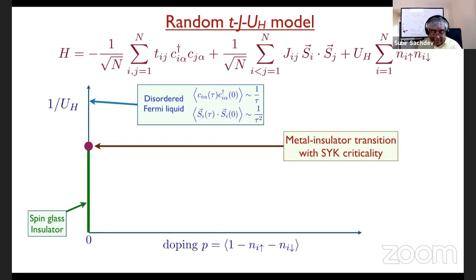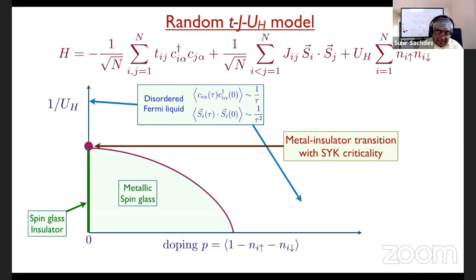So now, of course, I'll put the spin glass insulator all the way up to that point. Now we want to dope it. At very high doping, again, we expect a disordered Fermi liquid. No surprise there, because it's just a dilute Fermi gas then. And therefore, the simplest scenario is that the spin glass boundary comes here. That's consistent with the scenario presented so far, which is the t-J model that we've studied. And then I've argued that this critical point here is what we've been studying.